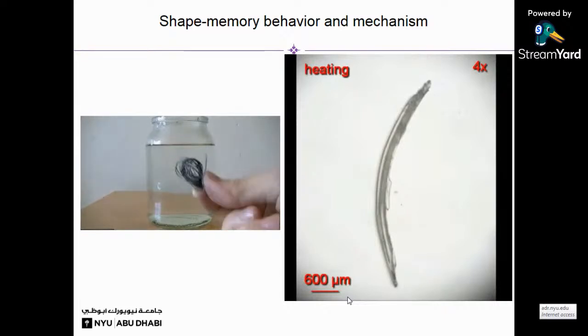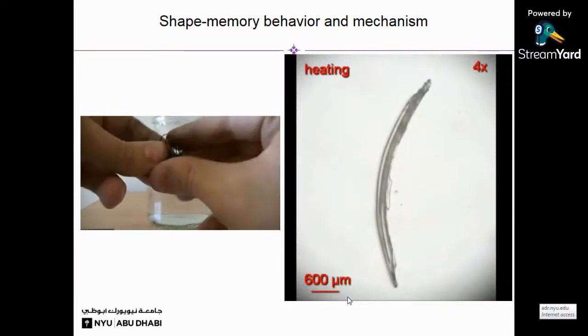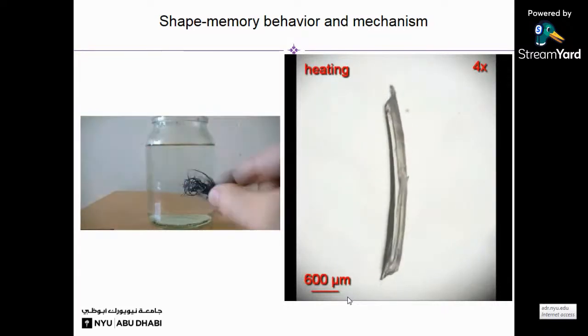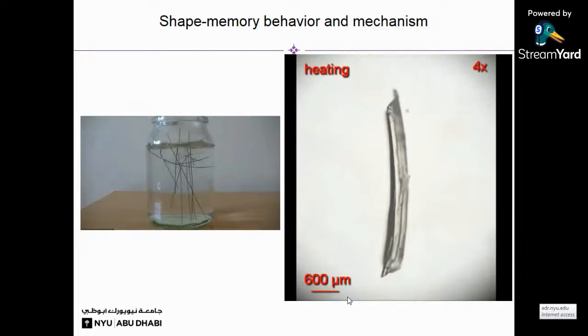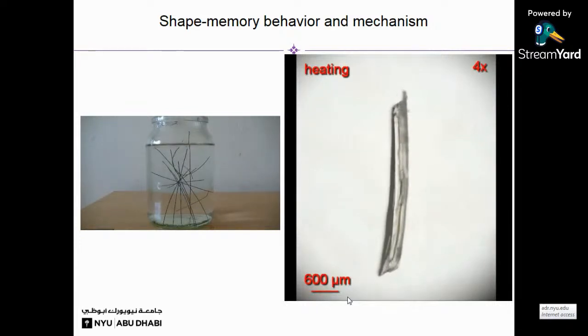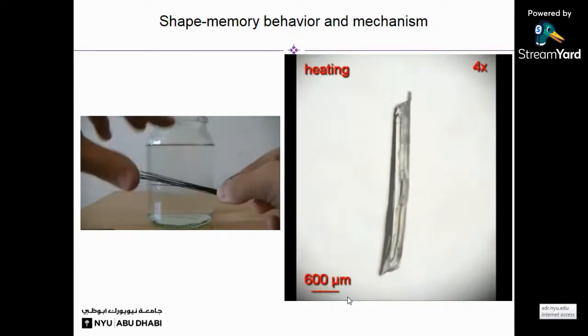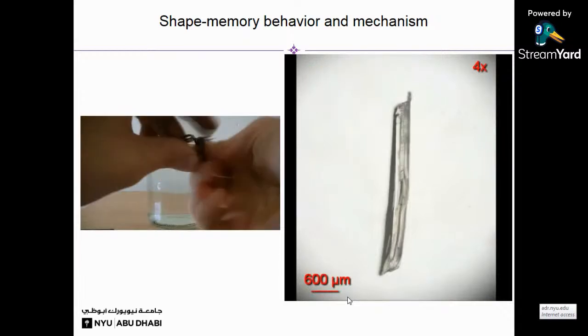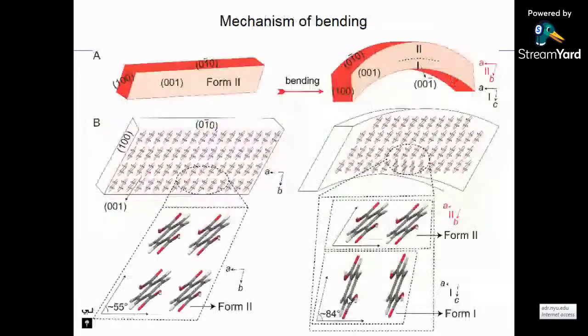The same behavior is shown by these terephthalic acid crystals also. You take a straight crystal, define a shape, make it into a bent shape. You heat it, it becomes straight. When you cool it, it comes back to its predefined shape, which is a bent shape. We have also proposed the mechanism. We have actually proved the mechanism.